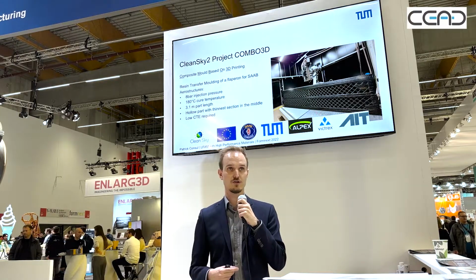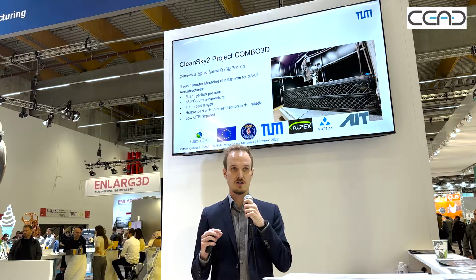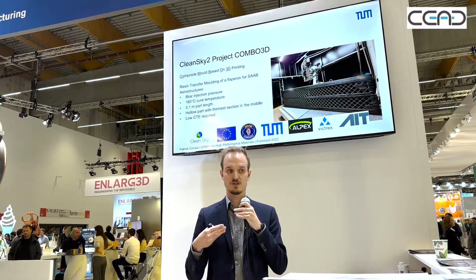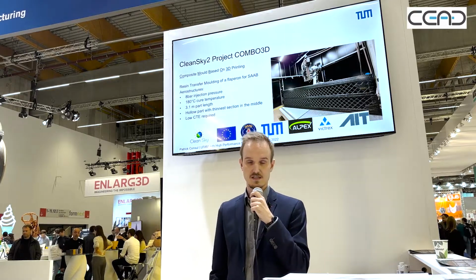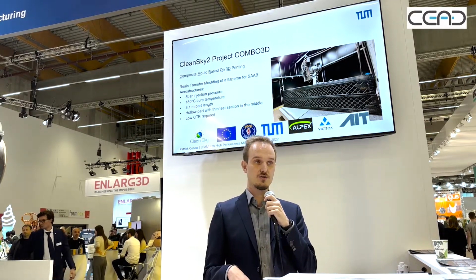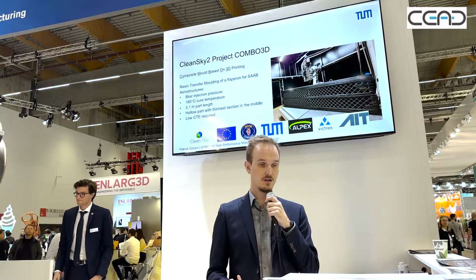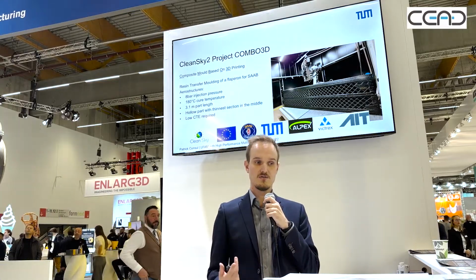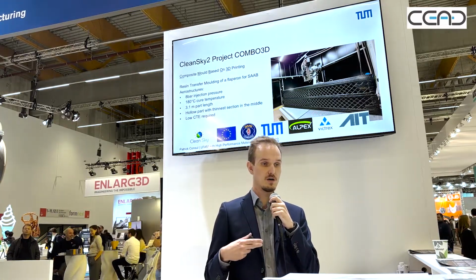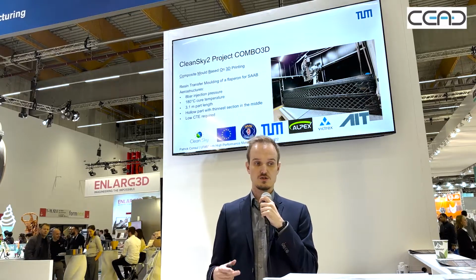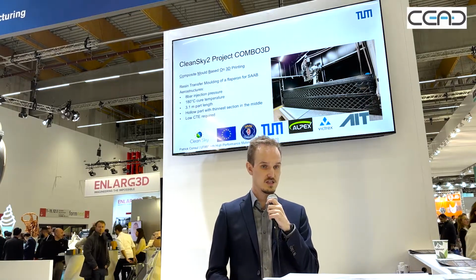It's a wing structure, and the thinnest part is in the middle, so you need cores going into the part from both sides. And the part you manufacture is a carbon composite shell, which itself has a very low CTE, so a requirement for us was to try and match this CTE as closely as possible.